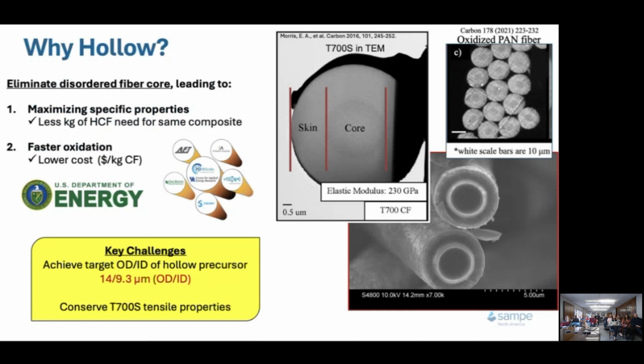So back to the hollow fiber. Why would we be looking at hollow? Well, it turns out some of these intermediate modulus carbon fibers, like Toray T700, have a structure of a skin and a core. Turns out that skin is far more oriented, has higher modulus, and can essentially handle more load than the core. And this structure, we believe, is an aftermath of insufficient oxidation. Even in the optical microscope, you can see the skin-core structure of the oxidized pan-based carbon fiber.